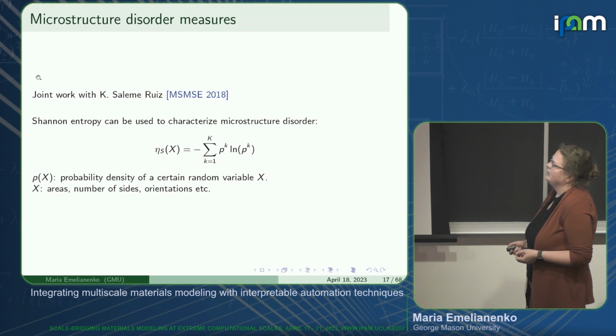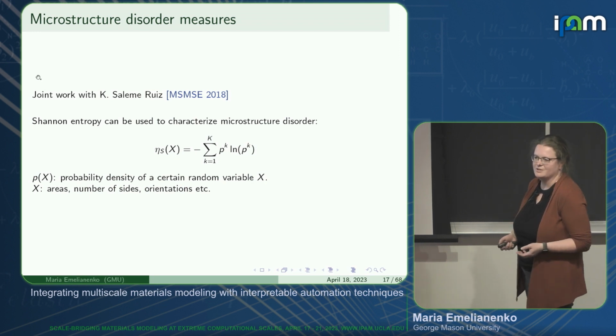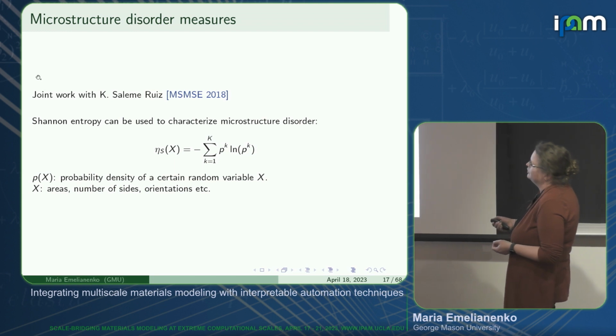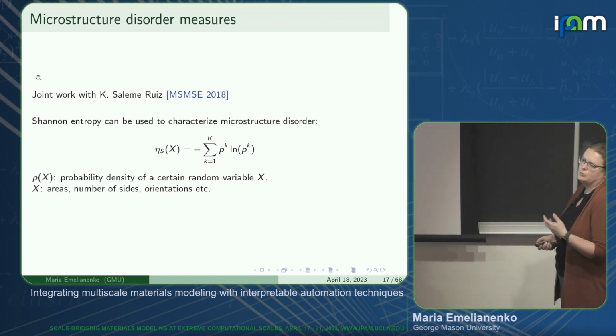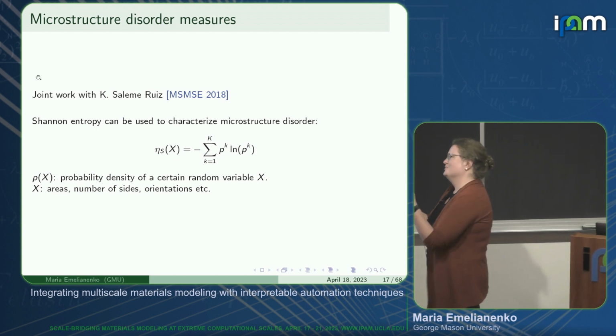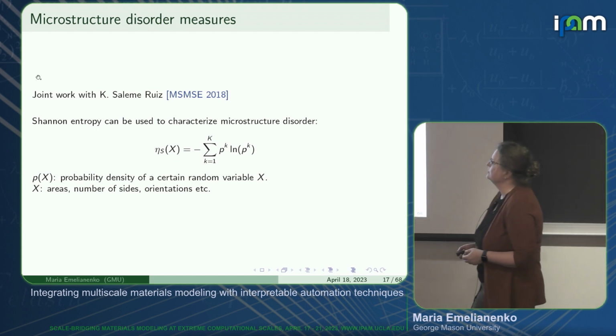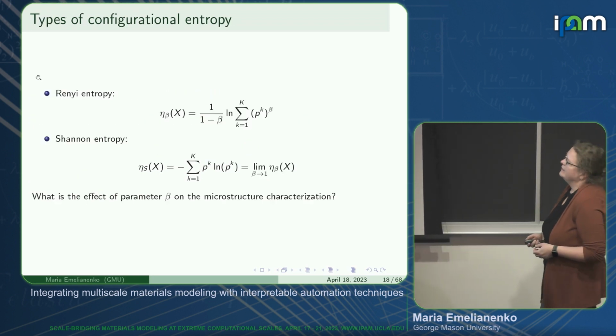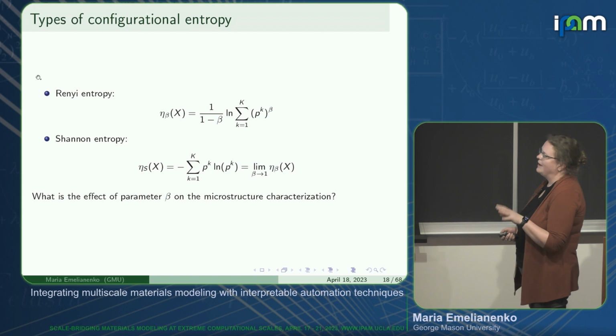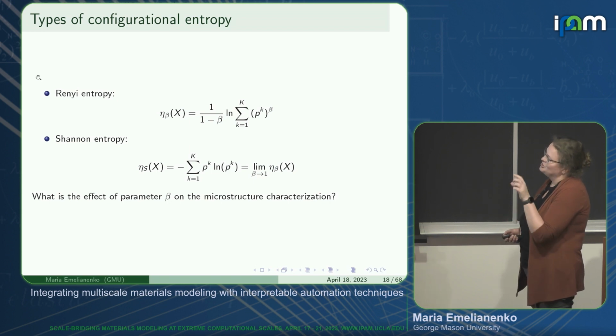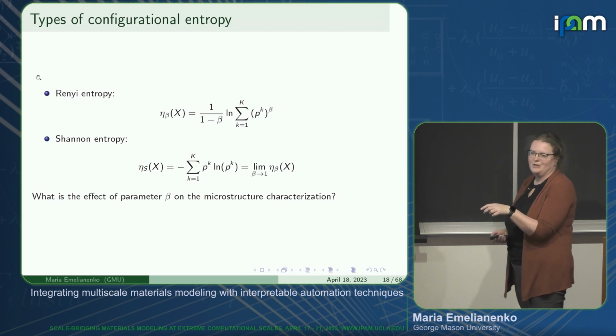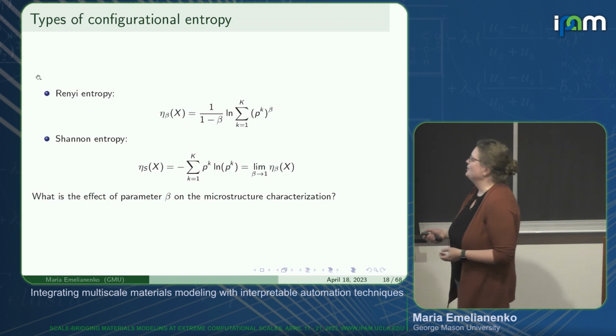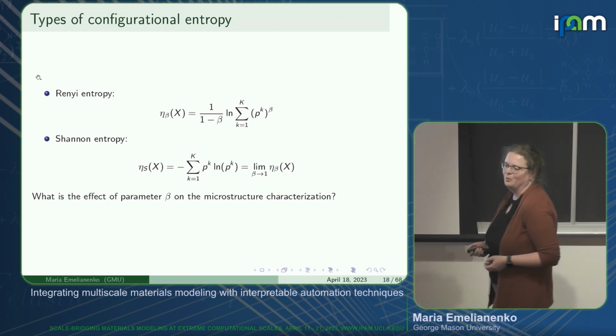One particular characteristic that we discovered, unrelated to additive manufacturing, is the microstructure disorder characteristic. It's a very easy concept to grasp. It's just the information entropy type of concept. But what you can do with it is look at any random variable, be it number of sides or areas or any roundness characteristic that you want to impose on a grain, and measure it. I wanted to draw your attention to this because we found some interesting results when we started changing this Shannon entropy and introduced the Rényi entropy, which has this parameter beta, which in the limit gives you the Shannon entropy, but it doesn't have to be 1.